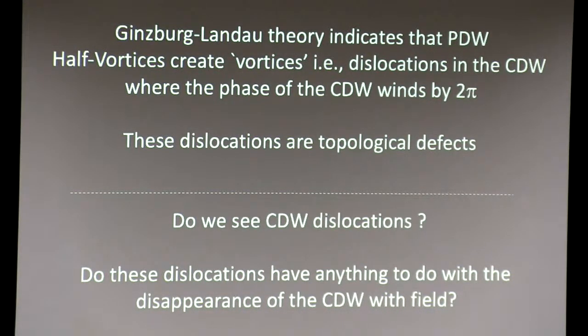When you turn on a magnetic field, you should have vortices of the superconducting order parameter, and you should have half vortices of the pair density wave. Theory indicates that when you have half vortices of the pair density wave, that should induce dislocations, which is a phase winding of the charge density wave.